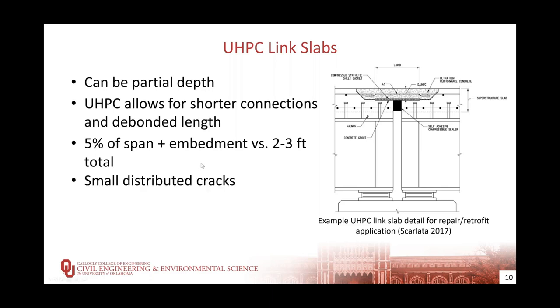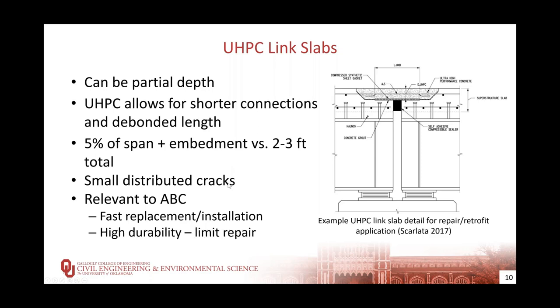UHPC also has those steel fibers holding cracks together. So instead of getting large cracks, we can get small distributed cracks, which has the potential to reduce water infiltration. And that's relevant to ABC because we can get a faster replacement of joints, potentially faster installation because we're placing less material.